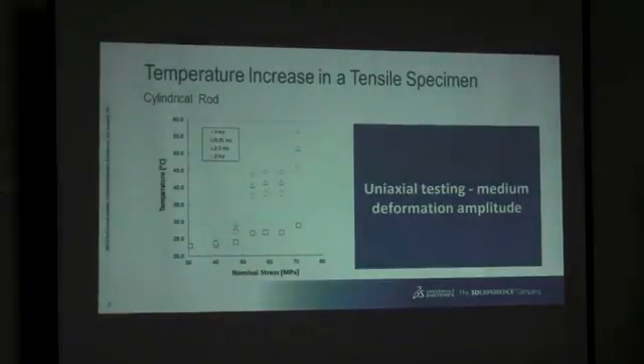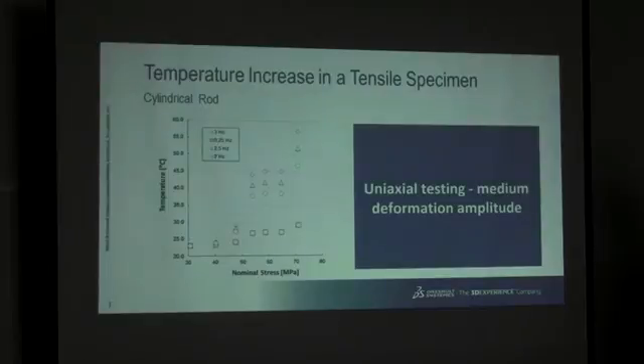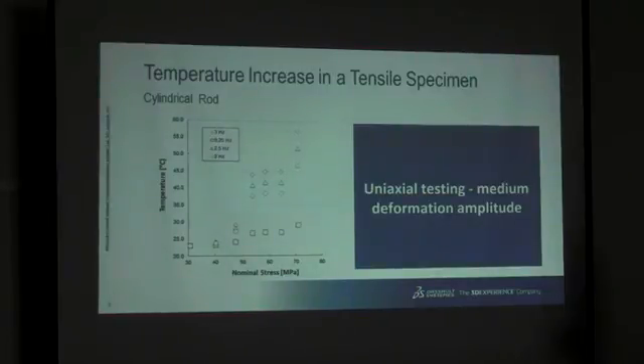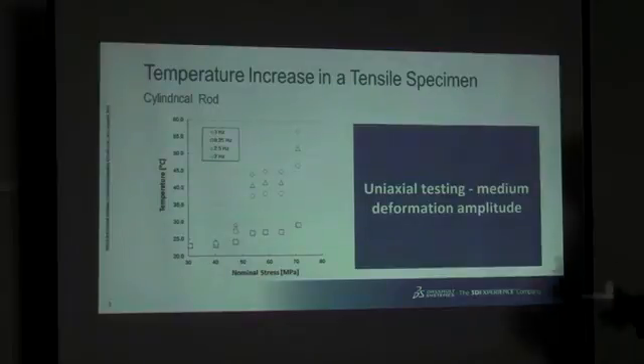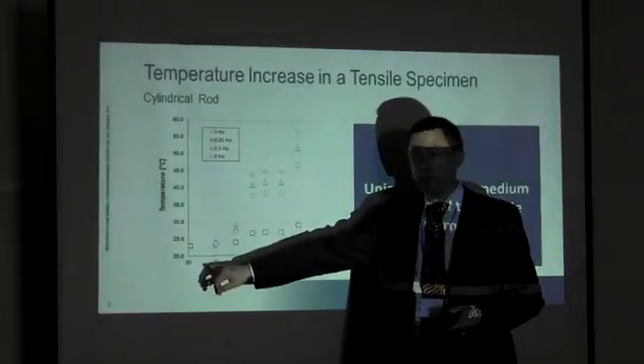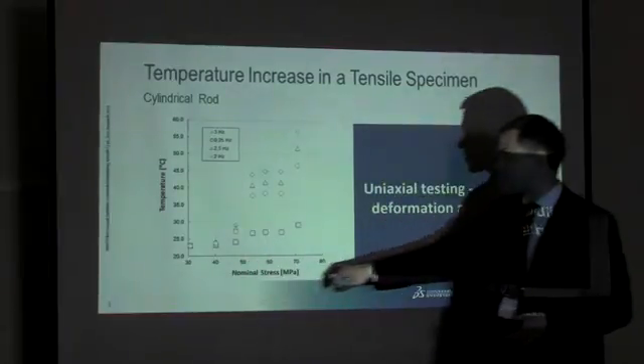We were talking yesterday, or rather we heard some interesting stuff yesterday about 3D printing, and the materials usually 3D printed. What I'm talking about is injection molded materials, extruded materials, or die-cast materials. So they differ quite a lot. But some of the basic investigations we did were, first of all, to look at the effect of frequency. So what you have on the vertical axis is the temperature. We always started out at 23 C being ambient, and then increasing the nominal stress for certain given frequencies.